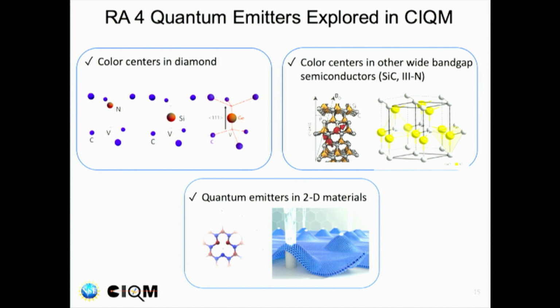And so what we're doing now is looking at different color centers in diamond. The first that was discovered is the nitrogen vacancy center, where you have a diamond lattice of carbon, there's a vacancy at one place, the V, and there's an impurity, nitrogen, which has one extra electron filling in one spot. It works like an isolated nitrogen atom, but it can't move around because it's held down. In many ways it looks like a single atom, like an ultra-cold atom, and that's the advantage of it. People showed that you can get a spin up or spin down with a coherence time of more than 3 milliseconds at room temperature, which is sort of amazing compared with other systems.